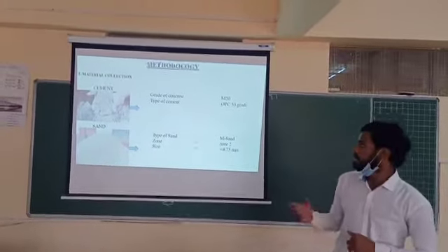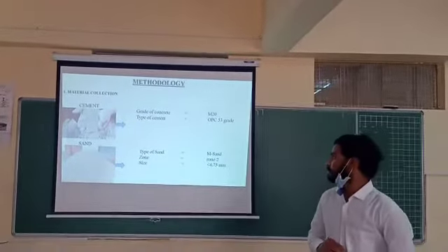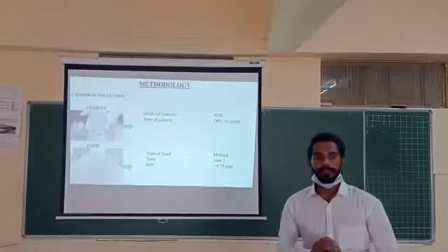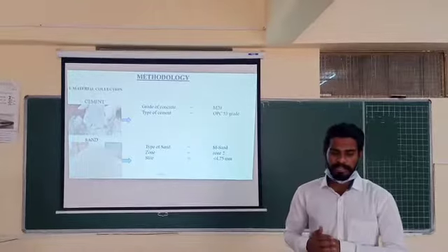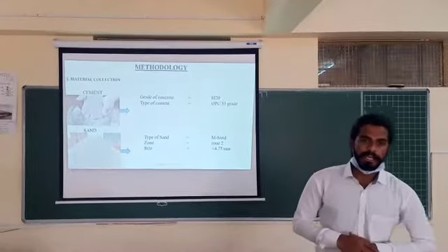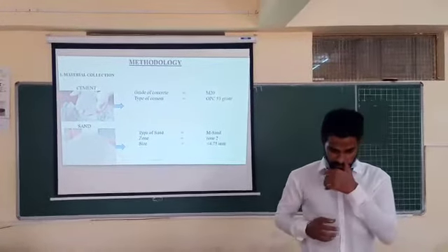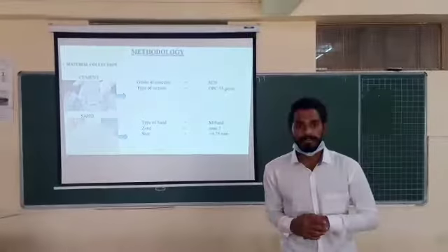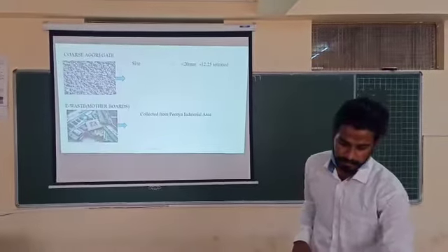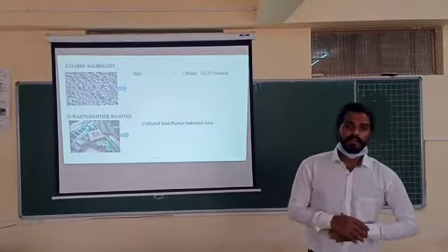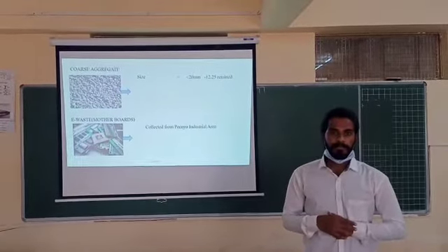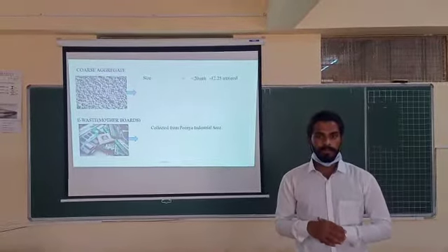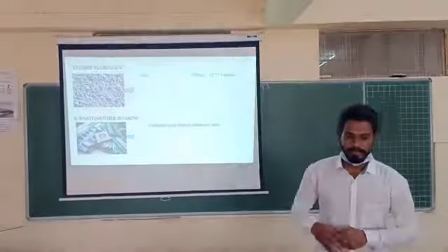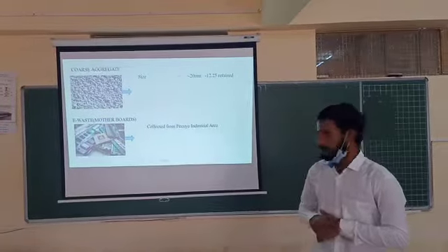Methodology. Here are some material collections. Cement: the grade of concrete is M20. Type of cement is Ordinary Portland Cement 53 grade. Sand: type of sand is M sand, Zone 2, size 0 to 4.75 mm. Coarse aggregate size passing 20 mm and retaining on 12.5 mm. E-waste collected from the industrial area.